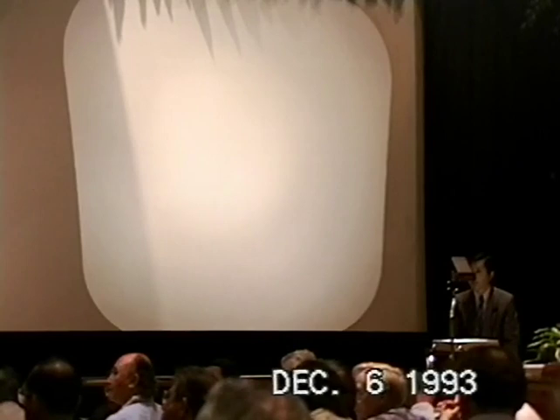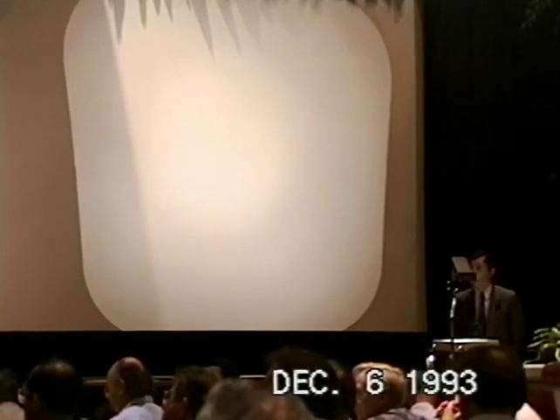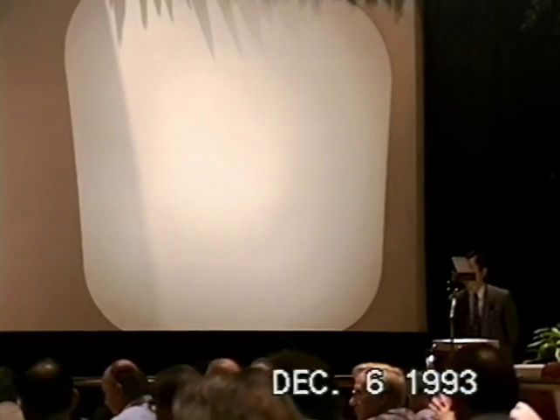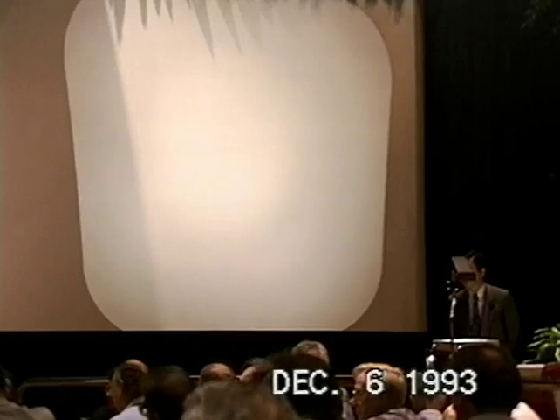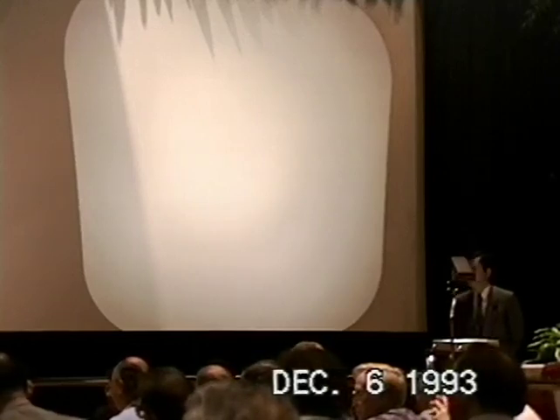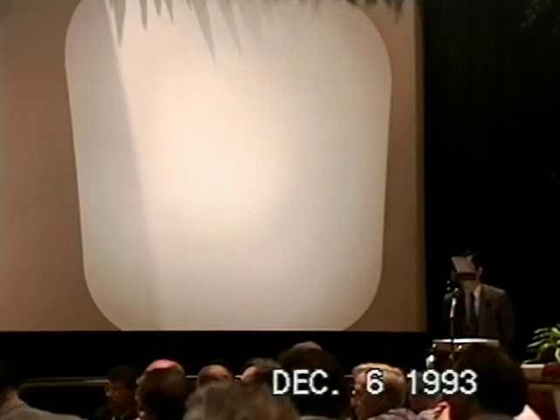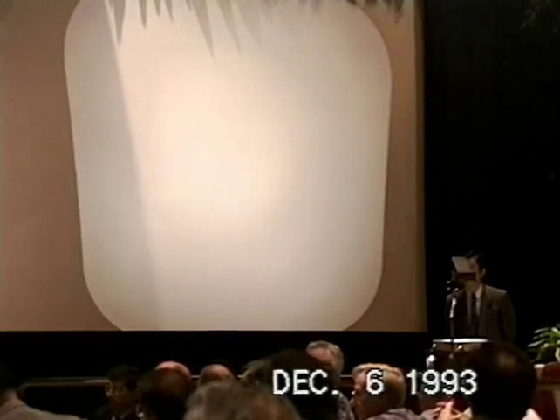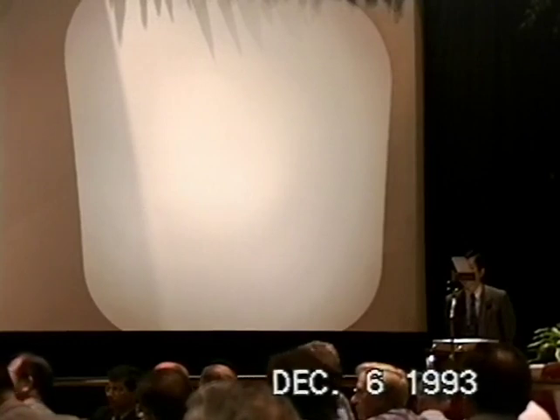Two comments to make. One with respect to thiourea. We found, as have many others, that indeed the same result occurs that with thiourea you can achieve a very high deuterium to palladium ratio. But we found that after a number of days, say 10, 12 days or so, the effect was lost. And in our experiments, and of course we had a high cell voltage because we were always electrolyzing water, the effect was lost, and often the loading ratio went down less than you would get without that. And we think the thiourea was oxidized and destroyed on our anode.